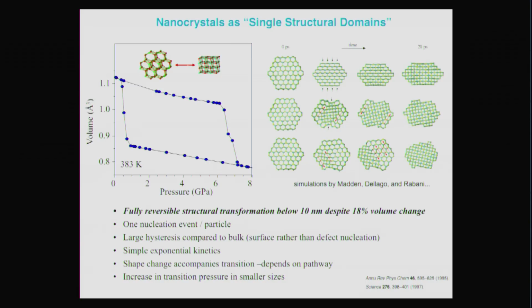But another thing that's very interesting about this that's quite fundamental for energy is that these transformations could take place with a 20% volume change of the crystal. The crystal can change from one structure to another with a 20% change in volume and then pop back again and just go back and forth like that, remaining a single crystal. If you take an extended crystal and try to do that, it will break up into domains because as the small domain grows inside the larger one, with the enormous volume change, as the domain becomes large enough, eventually it exceeds the dislocation energy formation in that solid, and the crystal will essentially crack into pieces. That's what happens in a normal bulk material.